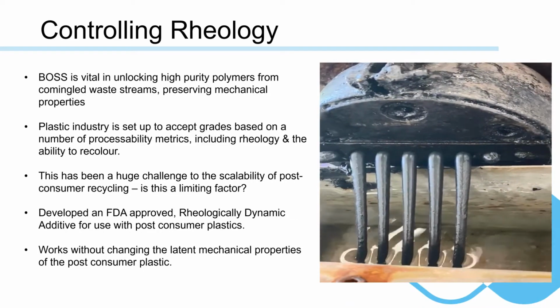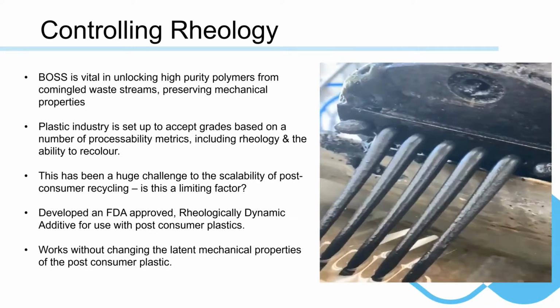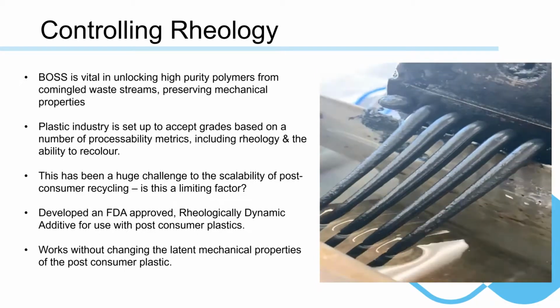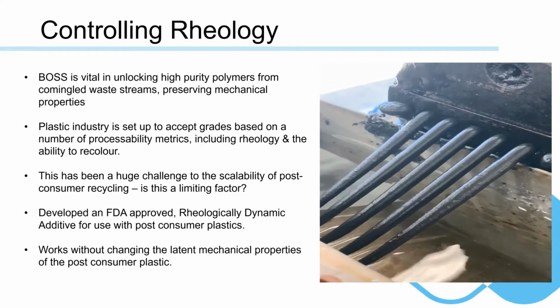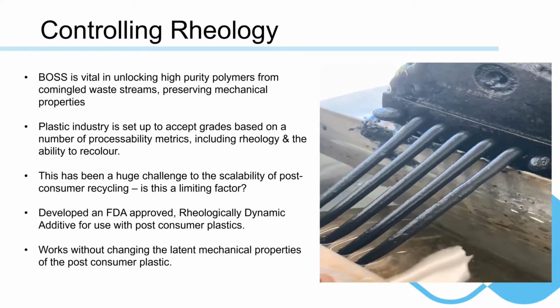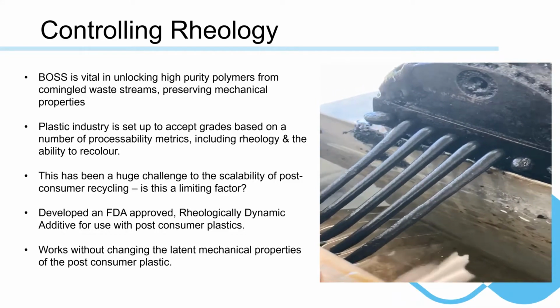So for example, if we want to sell our polyethylene into an injection grade application, our rheology was too stiff. Our material was simply too stiff to inject it at the rate that they required. Likewise, if they wanted to blow a bottle out of our recycled grade, it was too runny. It wasn't stiff enough. So what we did at Impact is develop a FDA-approved rheologically dynamic additive, which we borrowed from the food processing industry, for use with post-consumer plastics. It essentially uses the same recycled PE as a polymer carrier, which allows us to sell a 100% recycled grade once compounded. And the additive works without changing the latent mechanical properties of the plastic.